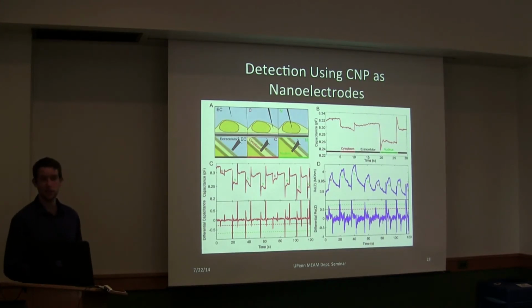So using the same technique, just with a CNP that's pressurized to the point where there's no fluid in it, we can monitor the capacitance signal as it penetrates the cell. And if you notice, the magnitude of the signal change using CNPs as these nanoelectrodes is much smaller. So before we were looking at a few picofarads signal change. Here we're looking at tens of femtofarads. So it's about 3 orders of magnitude difference in signal change.